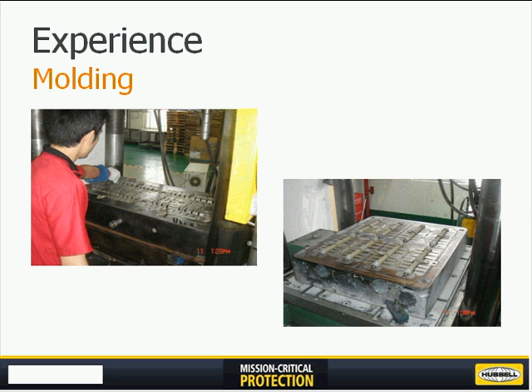The critical test for this is going to, of course, be water penetration for those who are familiar. Water penetration subjects the insulators following molding to a 100-hour boil in salt water, and then it, of course, stresses it with a power frequency test, which is a dielectric withstand test for the insulator, as well as a steep front impulse, and followed up with a temperature rise.